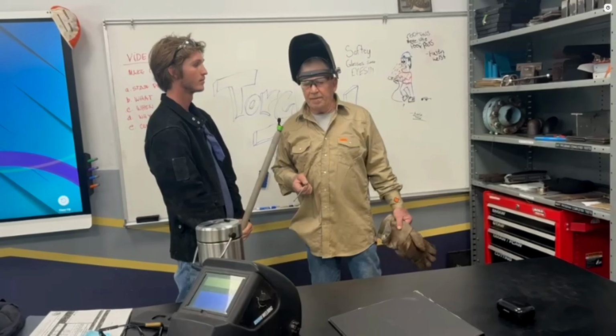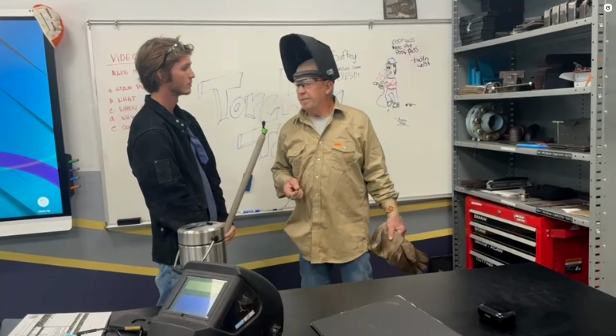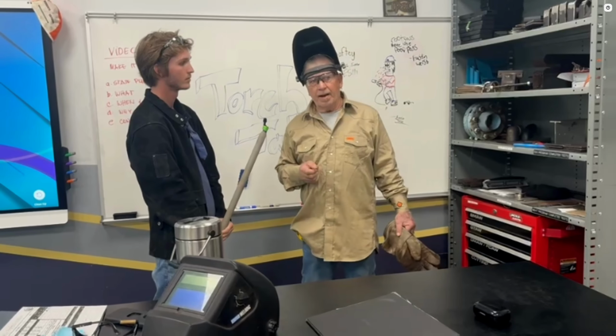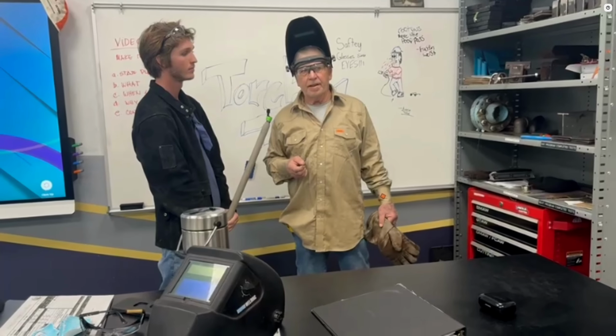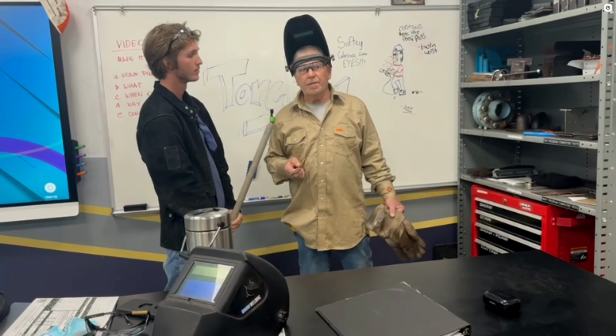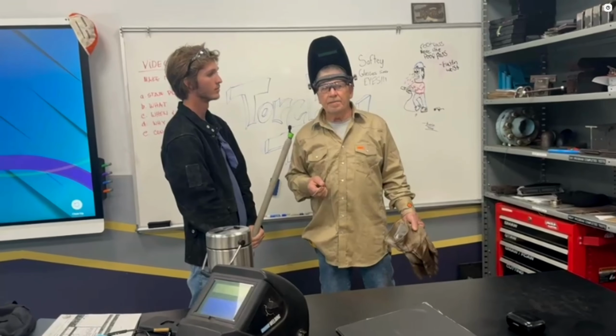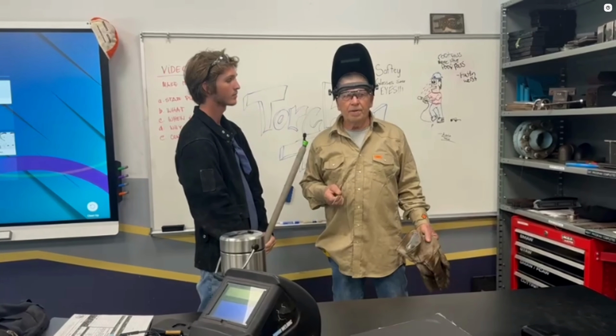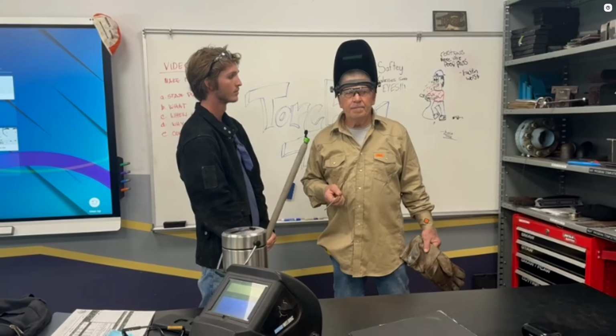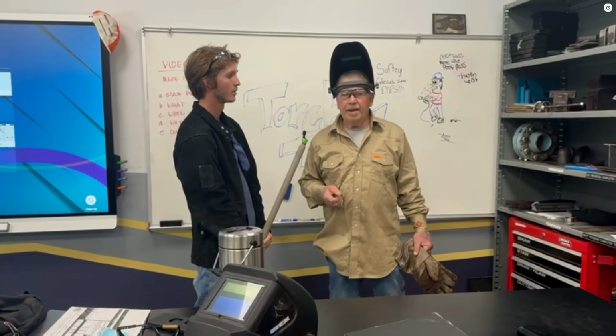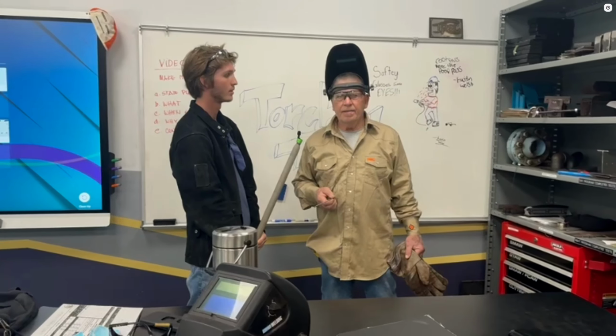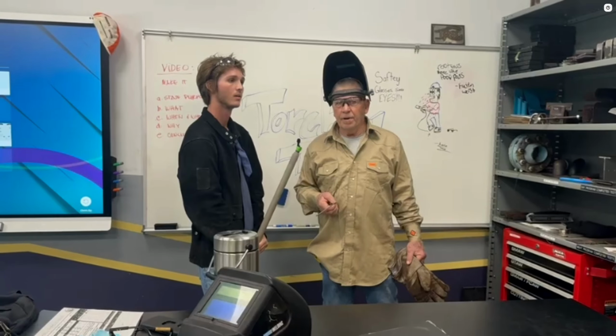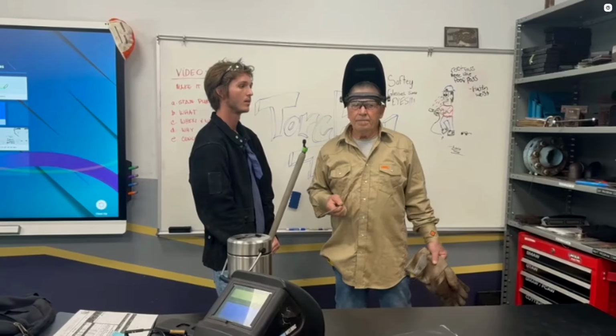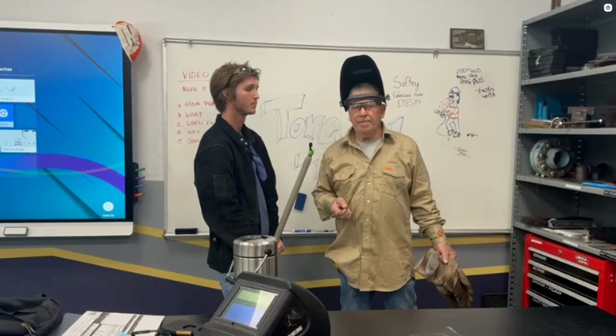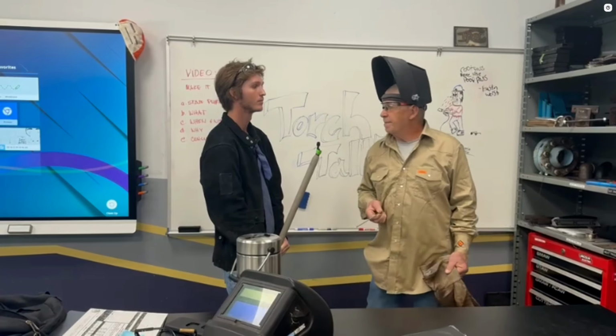Finally, we've got low hydrogen electrodes such as 7018. They're designed to minimize moisture and hydrogen in the weld to prevent cracking. So it's mostly used on high strength steels or thicker joints. They produce pretty strong, ductile welds with a smooth bead and must be kept dry. That's why they're always in that oven like our baker showed you guys.